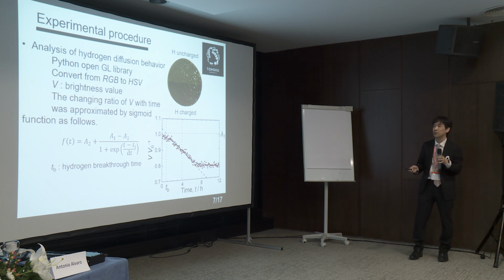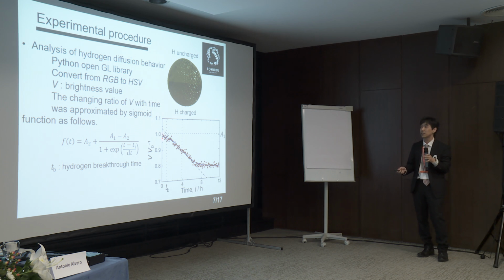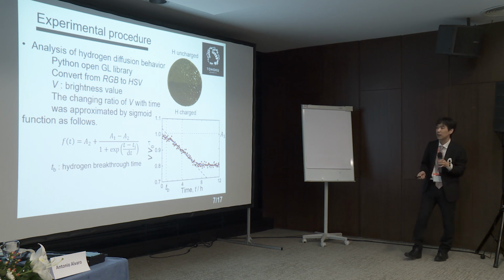The changing ratio of V with time was approximated by this sigmoid function. The red dots indicate the brightness value ratio, and the blue line is a fitting curve. Hydrogen breakthrough time was defined as the intersection of the tangent line at the inflection point and the initial brightness value ratio.